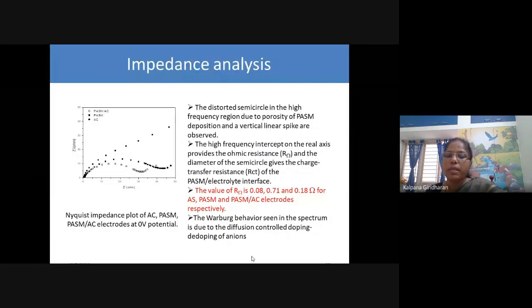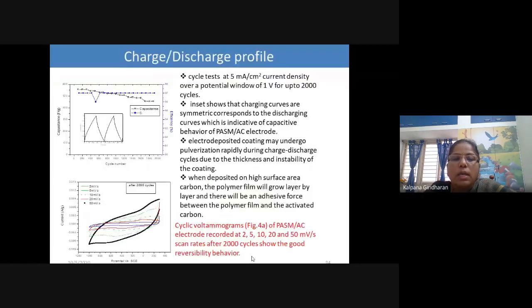This is the impedance analysis. Solution resistance, ohmic resistance, and charge transfer resistance are all obtained from this impedance plot. The Warburg behavior seen in the spectrum is due to diffusion-controlled doping and de-doping of anions.